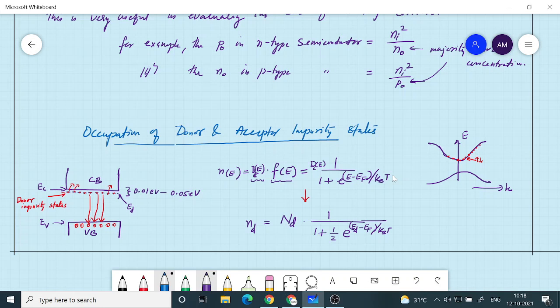So similarly, if you look at the filling up of the donor states, the number of states which are filled is equal to the total density, which is given by the doping concentration. This is the doping concentration multiplied by some probability function, and in that probability function there is an extra half. That is the only difference, and that difference comes from the argument which I said. Since we have not seen the derivation of the Fermi-Dirac distribution, we will not go into the derivation of this particular expression. This expression gives you the probability of filling up the donor states, and it comes with a half as an extra factor to this exponential term.